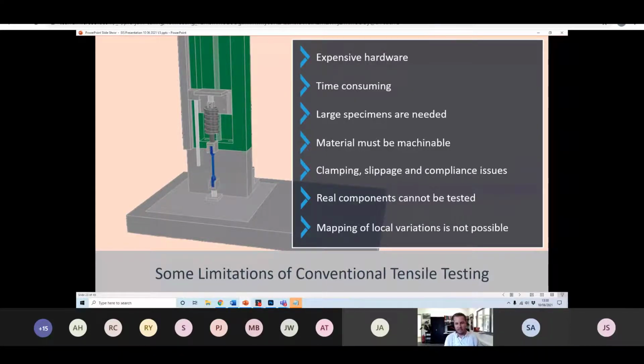Okay, so mechanical testing or uniaxial mechanical testing, as we talked about before, is unquestionably the gold standard. We mentioned that in a previous slide for characterizing the strength of materials, but it too suffers from some limitations. They can be addressed in most cases, but these might include the fact that the machine is very expensive, so you have high capital setup costs. Time consuming as well. Really what I mean by that is not the test itself, which tends to be quite quick. It's actually the preparation of specimens, because you've got to get coupons machined and you've got to have access to machining facilities, or you've got to outsource that process, and that can take quite a lot of time. But in addition to that, you need to make sure that the material can be machined. Not all metals are very easy to machine. You can suffer from clamping and slippage difficulties or compliance in the system. You can't, of course, test real components. You've got to machine coupons, and also what's not possible, like in hardness testing, is mapping of local variations in properties. Okay, so some limitations there.